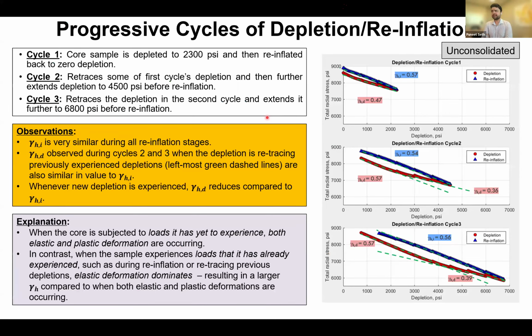There were some tests where we did progressive cycles of depletion and reinflation, meaning that we did multiple cycles. So this is, for example, cycle 1, 2, and 3. In cycle 1, the sample was depleted to a certain pressure and then reinflated back to the original pressure. In cycle 2, some of the depletion in the first cycle is retraced, but then the sample is subjected to a higher depletion than the first cycle and then reinflated back. Cycle 3, again, retraces the depletion in cycle 2, but then subjects the sample to a higher depletion than it has previously observed, and then it's reinflated back.